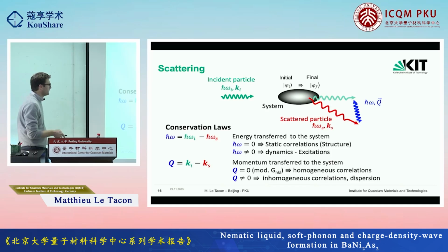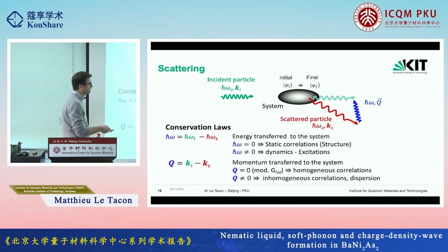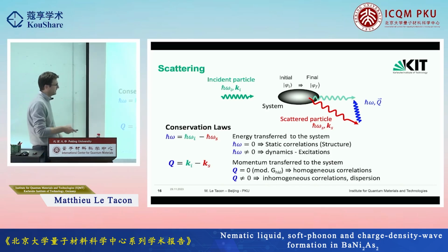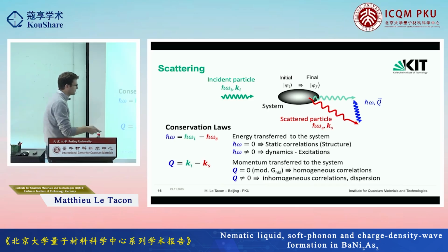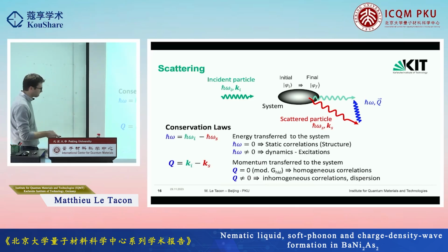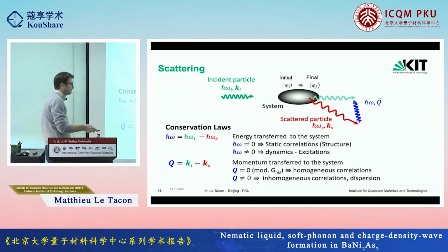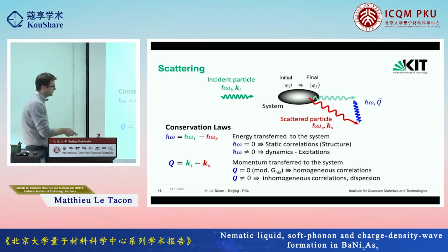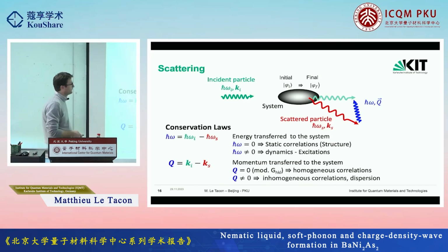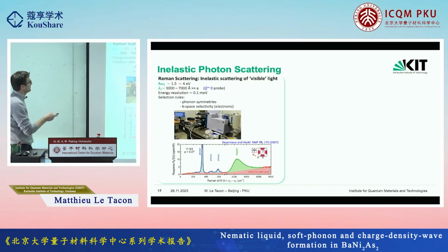And you have some momentum transfer, which allows you to either probe homogeneous correlation, so Bragg reflections, for instance, and you can look at the structure of the system by diffraction, or inhomogeneous correlation and probe the dispersion of your excitation if you work at finite Q different from any Bragg wave vector. And for today, we mostly used this inelastic scattering in two regimes.